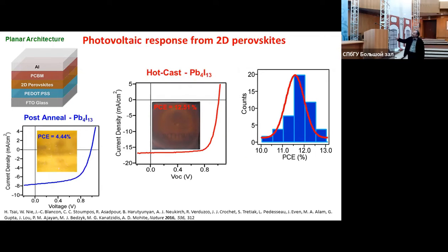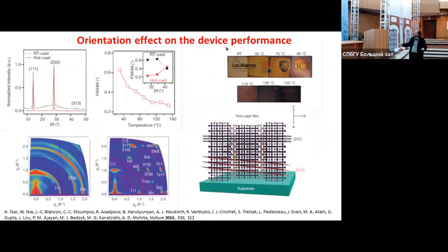And by using a planar architecture and his patented hot casting technique, we have been able to get 12% efficiency. That was the record efficiency at the time, with good consistency in the conversion efficiency. This is much smaller than the 3D perovskite, but it has other benefits. For example, you have a lot of organic content within this material, and this protects it from water. Water kills these perovskites.